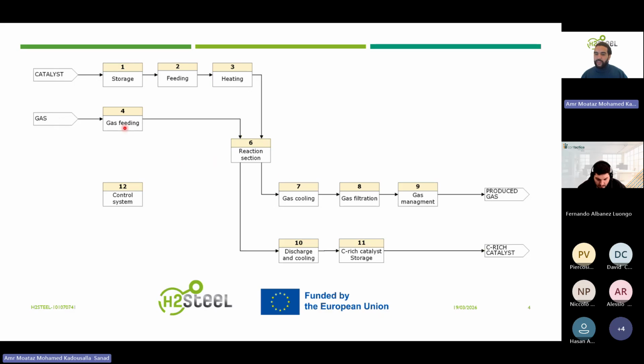The catalyst line starts with the catalyst storage at the 150 liters hopper, which is in turn placed over a load cell, allowing for precisely monitored feeding from the hopper into the heating screw. The heating screw is, as the name suggests, heated electrically and is used to heat up the catalyst to a temperature of up to 900 degrees Celsius.